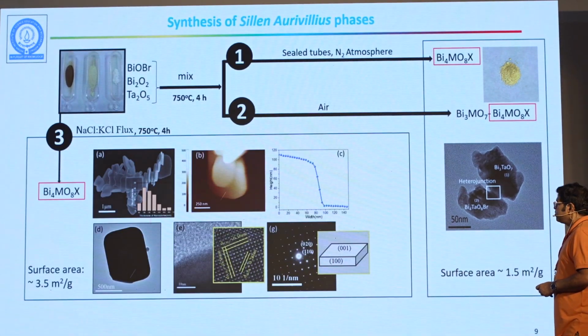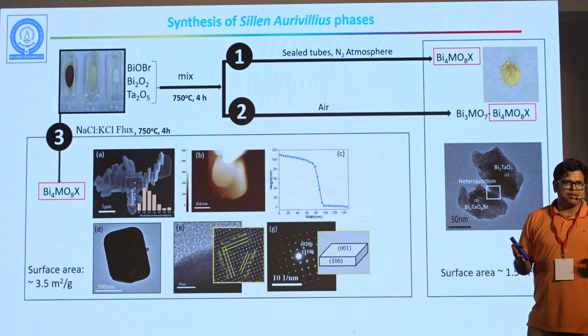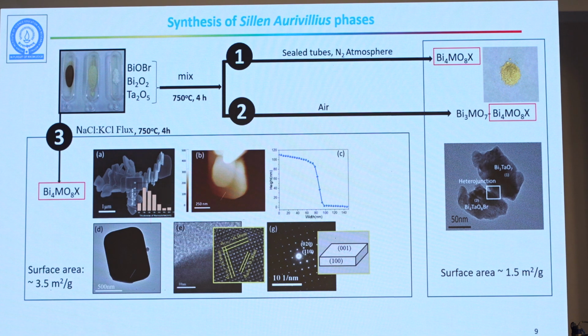So I'll skip most of the synthesis parts. We can synthesize them in various ways, but they are very beautiful. This is what I wanted to point out. You can see that they are single crystals. They are tiny single crystals. This is a high resolution image. You can almost look at the atoms here, or the rows of atoms, okay? If you look at the electron diffraction pattern, it again confirms that they are single crystalline, very beautiful structures. Then once you have a single crystalline structure, we know that crystals have different facets. In this particular case, this crystal has 001 facets, which is the bigger face, and the 001 axis is the polar axis, along which the reaction actually happens.